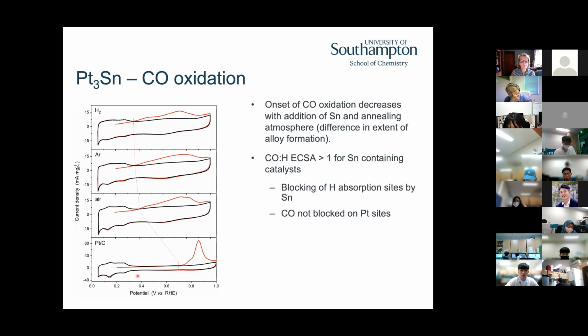I assume that most of you are electrochemists, but if you are a thermal catalysis person, you can sort of think of the potential scale as the thermal axis in terms of doing temperature programmed desorption, in terms of the red lines here, which are the CO stripping. In electrochemistry, we change the potential to turn that on. And what we're looking for is the lowest possible light-off temperature in terms of thermal catalysis, but the potential at which we start to see the CO oxidation, which we call onset potential in electrochemistry.